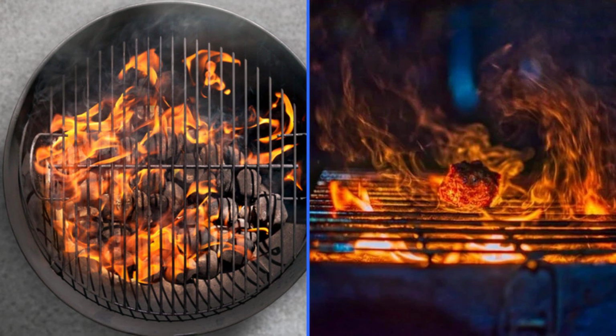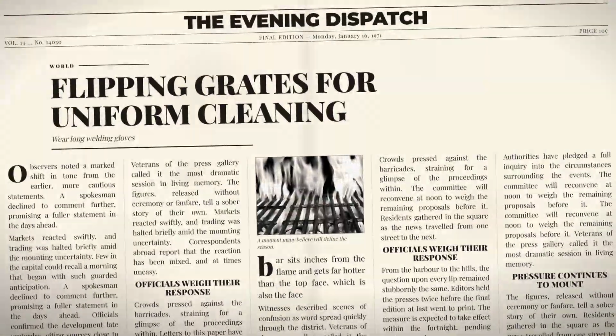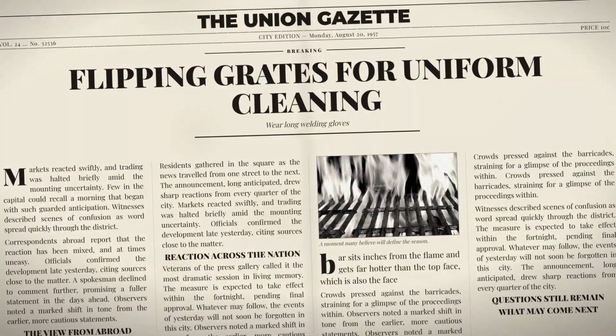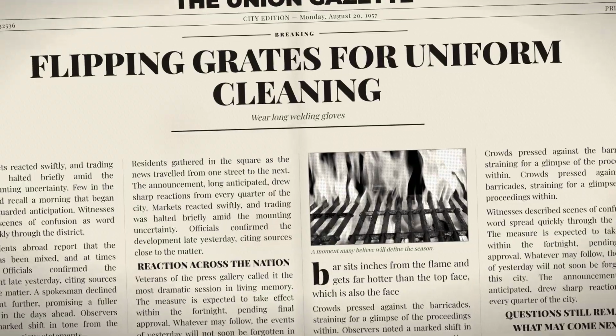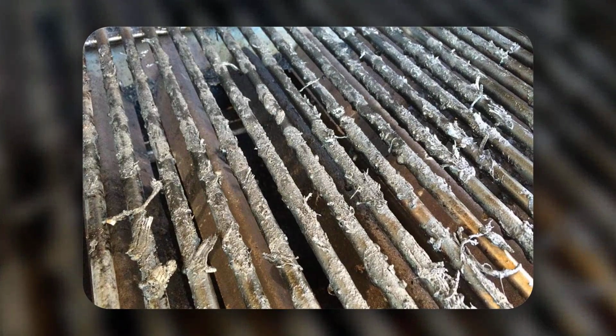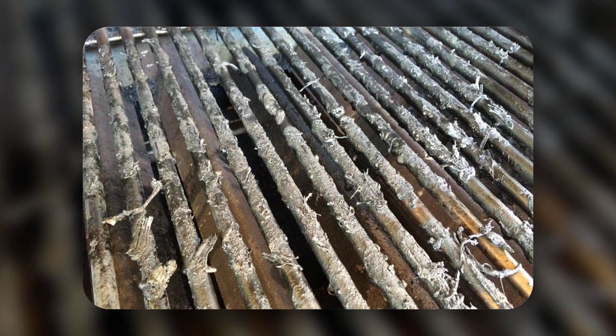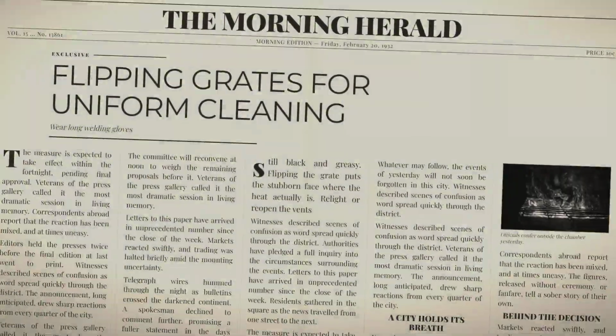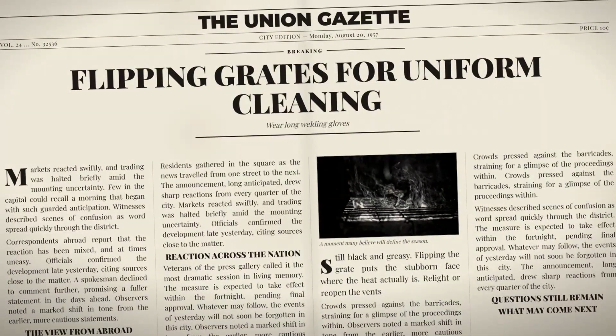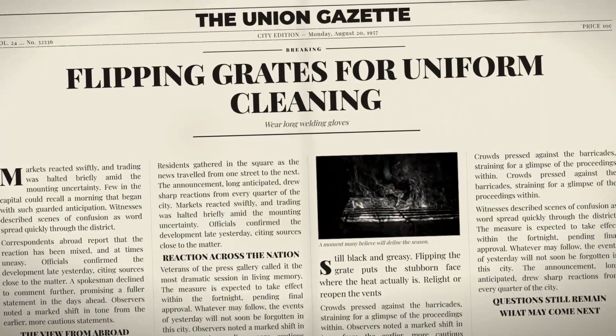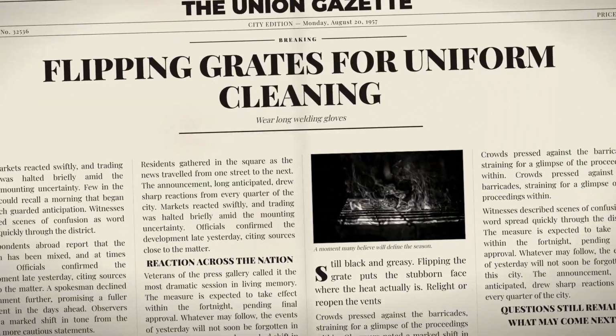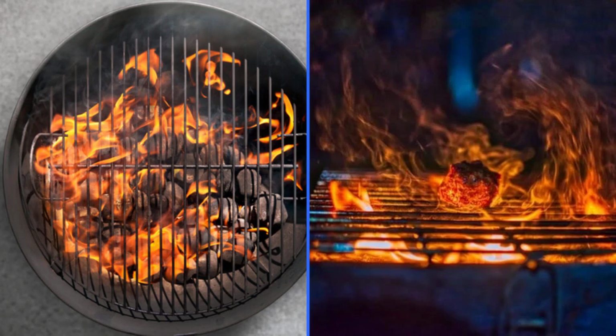Heat rises, but the fire is underneath. The bottom face of every bar sits inches from the flame and gets far hotter than the top face, which is also the face losing heat to the cooler air near the lid. That is why burn-off leaves the underside gray and clean while the cooking surface is still black and greasy. Flipping the grate puts the stubborn face where the heat actually is. Relight or reopen the vents and give it another 10 minutes with the lid closed.